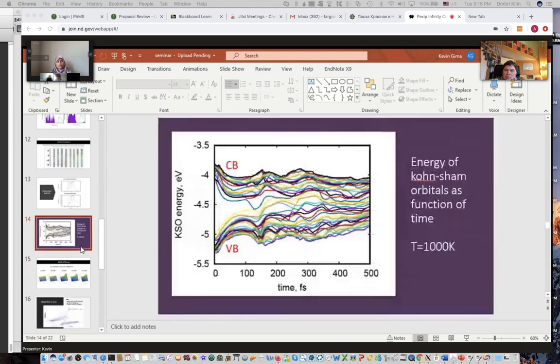And then here's how my Kohn-Sham orbital energies change with time. At time 0, we initially see that our band gap is around 1 electron volt, and then as time goes by, we see that the band gap essentially decreases to 0. So this band gap essentially disappears.